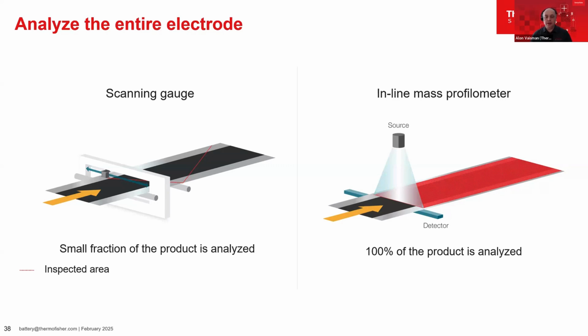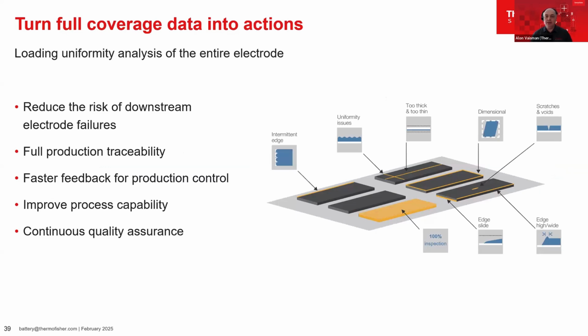Mass profilometry, on the other hand, captures a complete side-to-side loading profile nearly instantaneously, every millisecond. Operating continuously, it produces a record of the entire electrode roll and makes the information and the results available in real time to help make process decisions and monitor quality. Mapping the active material loading on the entire electrode enables one to get a better understanding of the coating process performance. Edge features are analyzed in greater detail, and it becomes possible to identify spot defects like streaks, divots, and high and low loading regions.